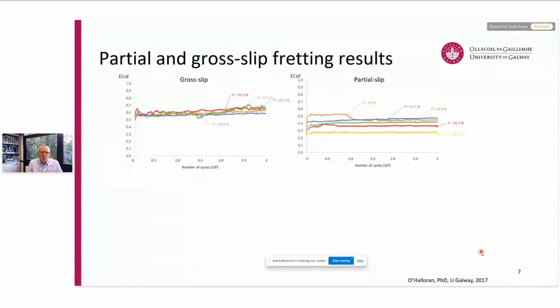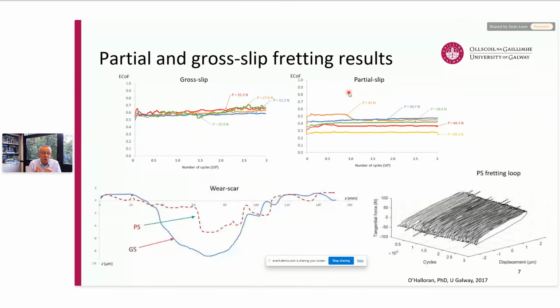And then just to show you an example or some sample of some of the fretting results from the pressure armor layer material shown here, that we've characterized gross slip and partial slip. And these plots here show the evolution of coefficient of friction for a range of different normal loads, typical of what's expected in the pressure armor layer contact nub groove region. And then you can see typical wear scars from our cross cylinder tests now in our fretting, in our piezoelectric actuated fretting rig. You can see the typical measured profilometry wear scars.